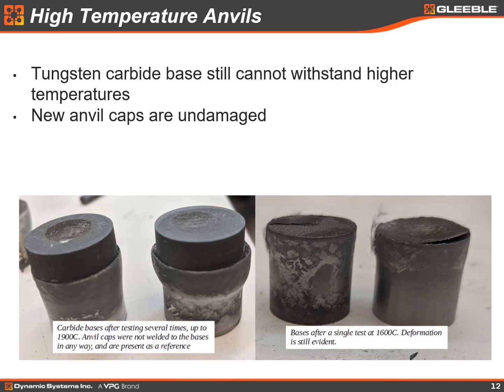Shown here on the left are the bases after those multiple tests up to 1900 Celsius. The anvil caps themselves are shown there for reference. They were totally undamaged and not welded to the bases or anything like that. And on the right are the bases, again, after a single test at 1600 Celsius. Even after one test, they show significant deformation.